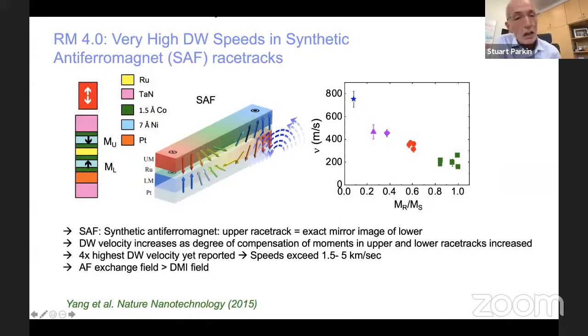But I wanted then finally, with regard to racetrack, to mention that truly, and I think Thomas Jungwirth gave a very nice talk about antiferromagnetic spintronics, I think the first talk in this series, a challenge in all magnetic nano elements is controlling the large dipole fields from the moments that are generated at the edges of magnetic wires or magnetic entities. And these fields are extremely large, up to 4 pi M, the magnetization of the material. And on the nanoscale they can cause significant interactions between magnetic layers within a structure or between devices, one device and another device.